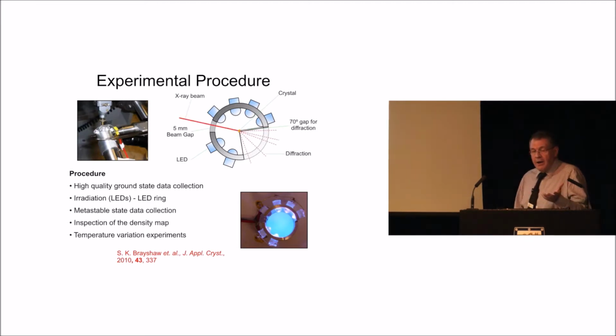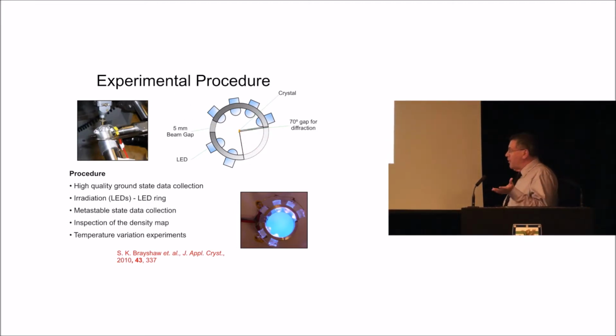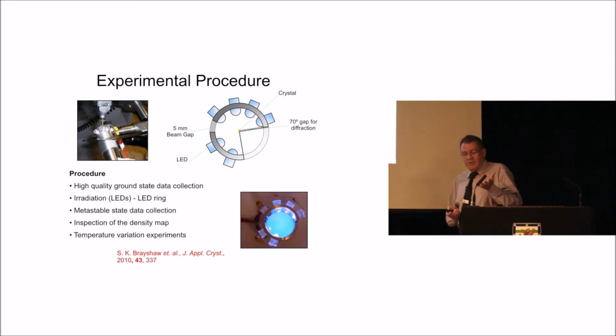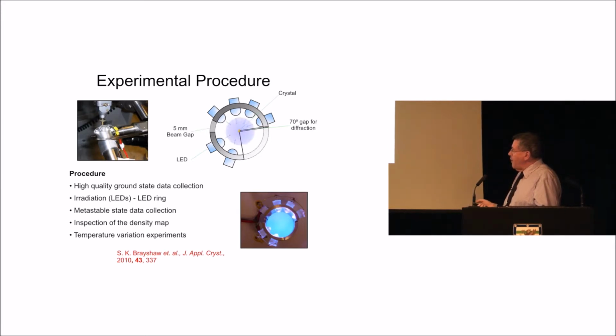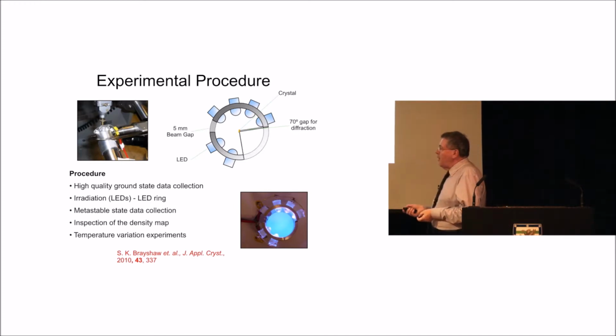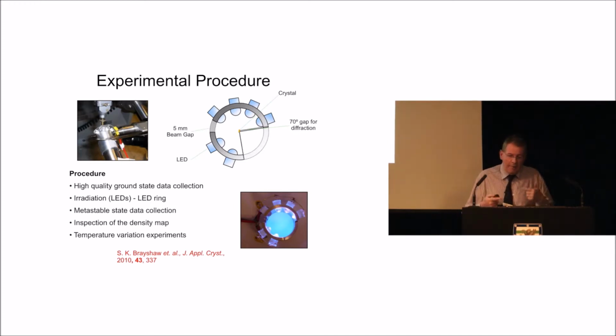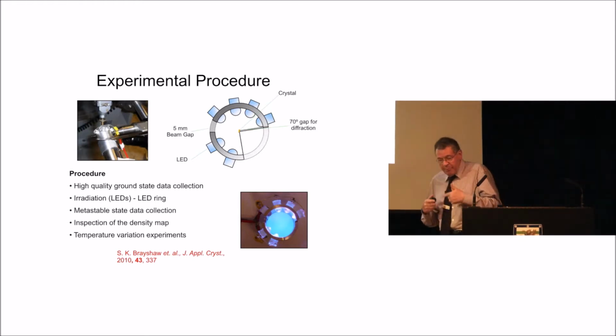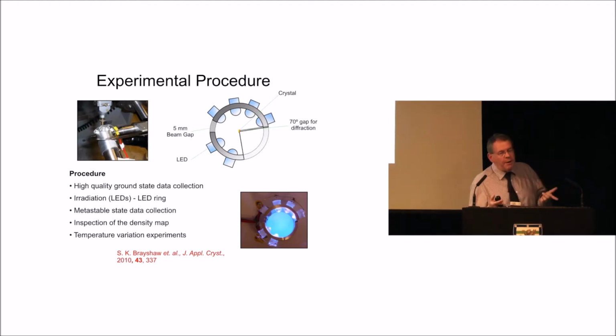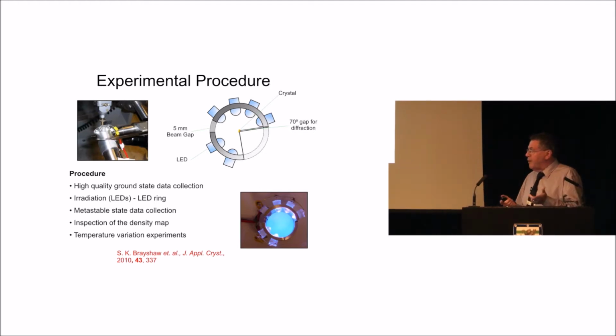That gives you a benchmark ground state structure. You then irradiate the crystal for a period of your choice to attempt to generate the metastable state, and then you recollect the data, you hope with some of the metastable state present, look at the electron density map, see if you can see a proportion or total conversion within the crystal, and then play with the temperature until that occurs.